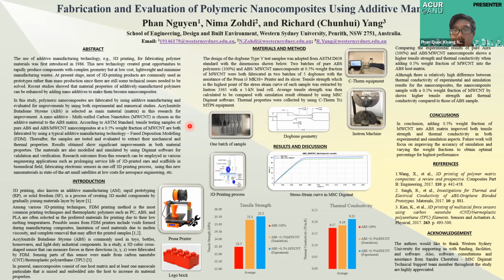Regarding the research methodology, our sample was called dog-bone, and it was designed following the ASTM standard. The model was first designed in SolidWorks, and then the whole CAD model is imported into this printer slicer for the toolpath. In detail, the toolpath contains the locations where the small nozzle here should move in the 3D plane in order to steadily create this complex geometry. To maintain consistency due to environmental impact, we decided to make 5 samples in one batch, and eventually we fabricated 2 batches. One is for the pure polymeric and one is for the nanocomposite for later comparison.